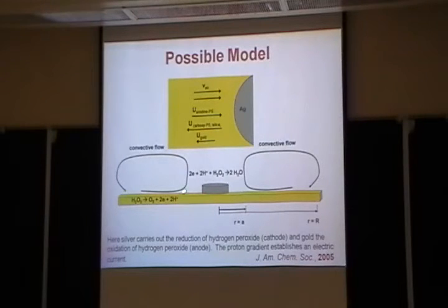But if you're a negative particle, as you come closer and closer, since this is the negative end of this metal pair, they get repelled. So when they come very close, they start to get repelled. So you have a zone of exclusion. If it's a positively charged particle, that's great. It just keeps going and then it goes up. So that's the story. It's a combination of electrophoresis of these particles and the electroosmosis of this fluid flow along the surface.